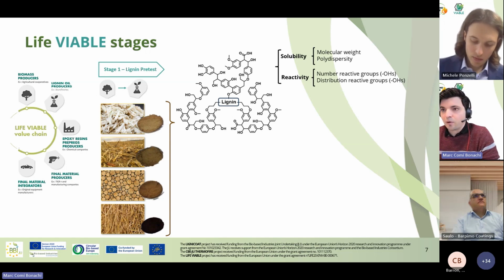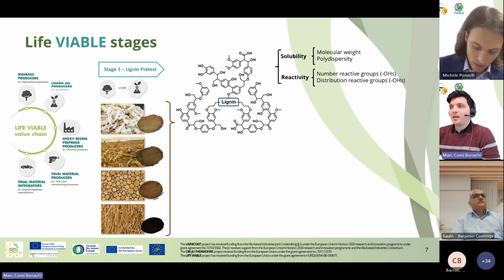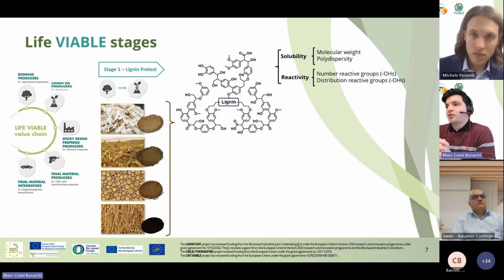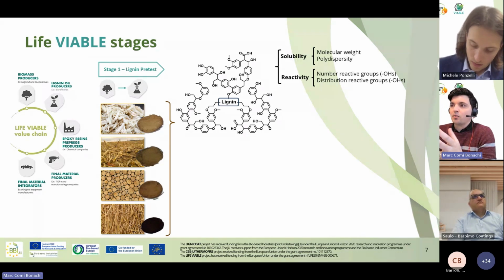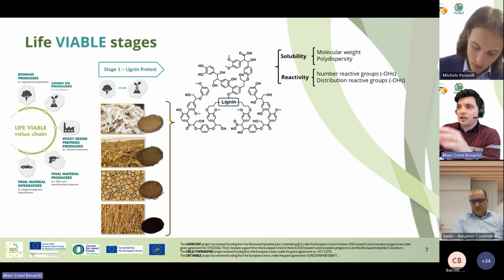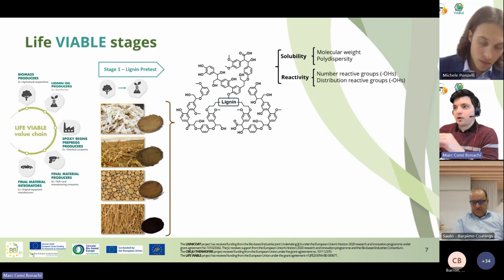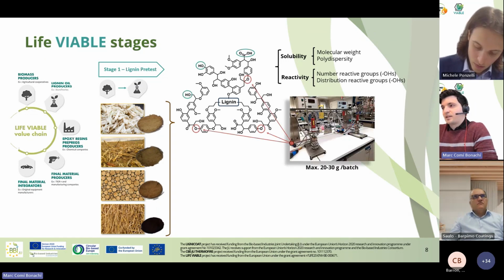The lignin that we receive from our suppliers has a high molecular weight and a high polydispersity. That means that the solubility is very bad, but also the chains are so different from each other that we need to get a more defined product. Also the reactivity: since the biopolymer is so dispersed and so big, the quantity of reactive points is very low. It's these reactive points that we are going to try to modify later and glycidylate.